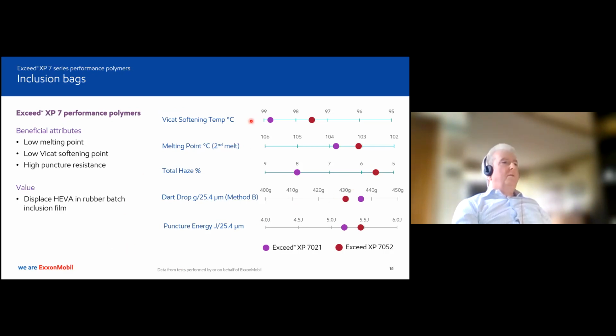Well, now that we've got these resins that have particularly good puncture resistance and low Vicat softening points, you can see that there is potential of these resins to go into this market. I don't have any data on this at the moment. This is more, I would say, a potential market to look at, but it's definitely an interesting one. And I guess if you had to pick one of these two, you'd probably go for the 7052 first, because it tends to have the lower temperature attributes that you're looking for.